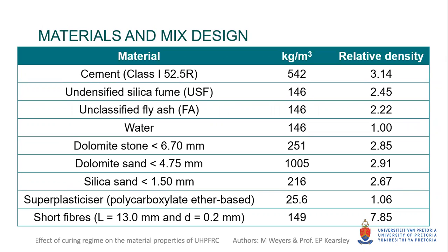A Class 1 52.5 R Portland cement with a relative density of 3.14 was used for the mixture. Local streams of waste materials, such as fly ash and silica fume, were chosen as cement extenders, not only for the economic benefits, but also to increase the workability and efficiency of the mixture, as well as the mechanical properties.